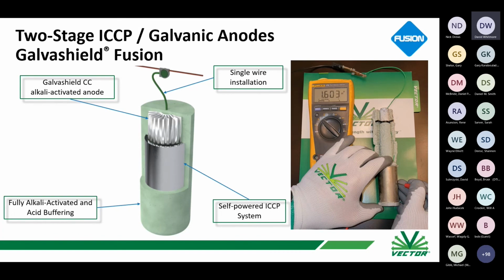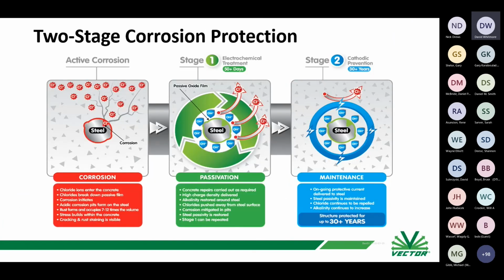So essentially you pass a higher level of current initially to passivate the steel. And that's a little bit more clear in this graphic here. So the intent is to pass more current initially to passivate the steel. And then you essentially will switch automatically to a lower maintenance level of current to keep the steel from corrosion from reinitiating.